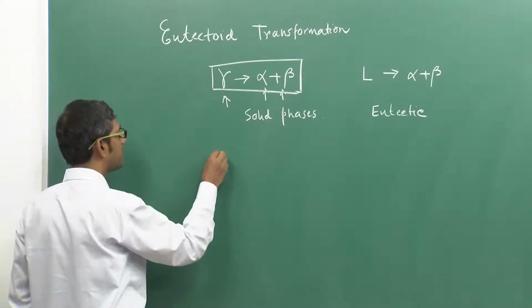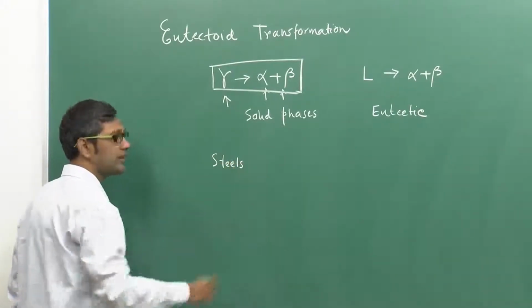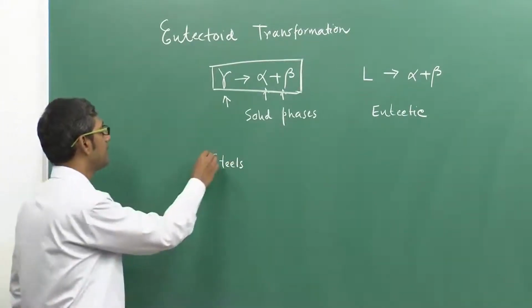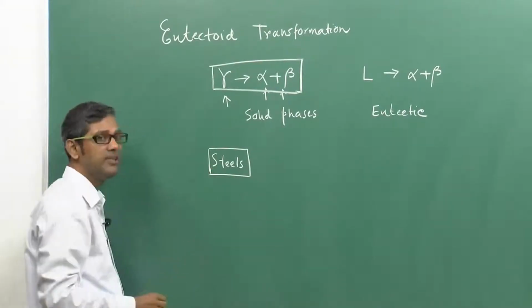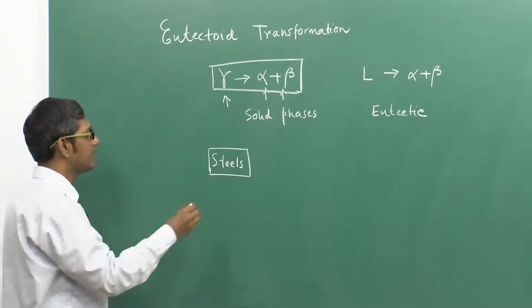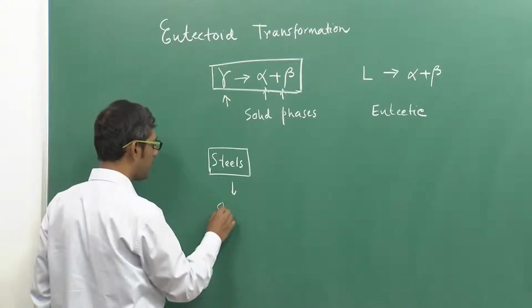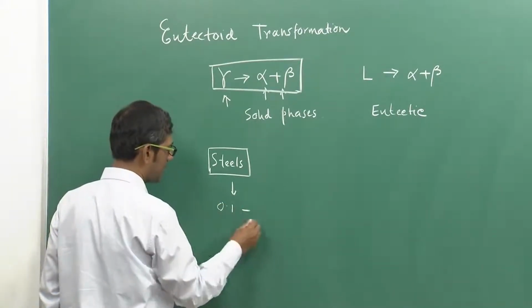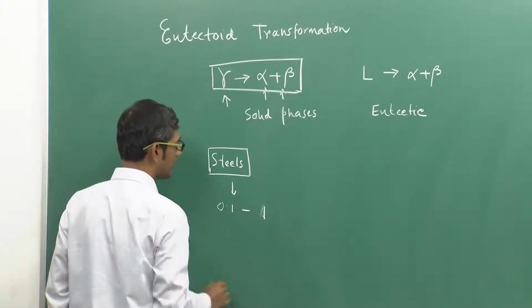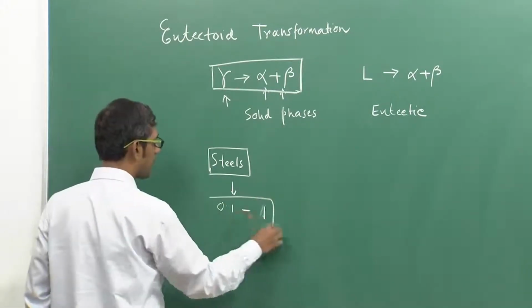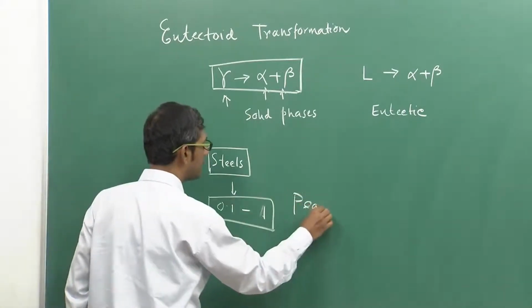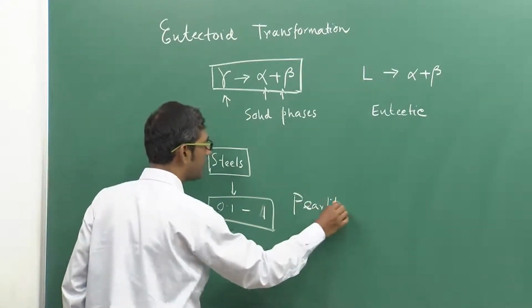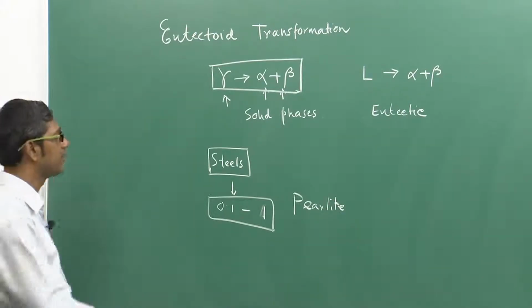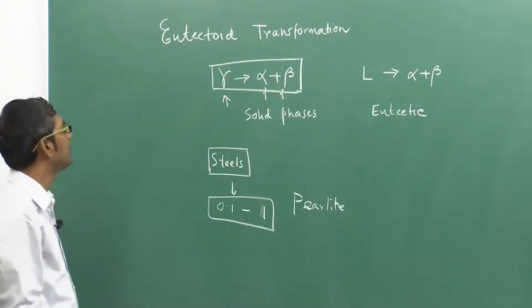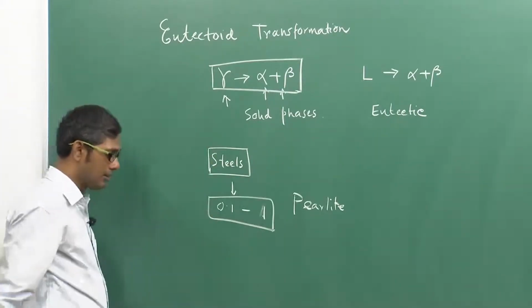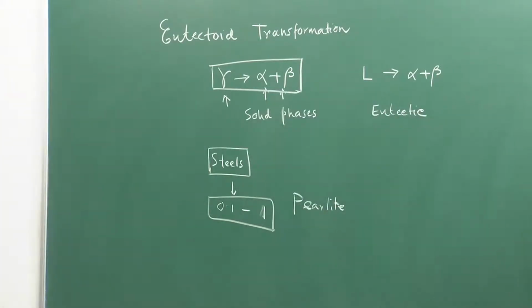Remember, the eutectoid transformation is very important in steels. So most of our discussions will take examples from steels and explain how the transformation happens. Steels with a composition from about 0.1 to, let us say, 1% show the product known as pearlite, which is well known to the metallurgical and material science community. This pearlite is nothing but a combination of two phases formed because of the transformation of the high temperature phase gamma. That is the important aspect which you should remember.